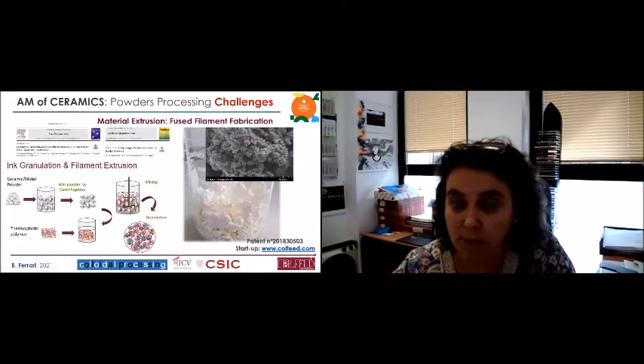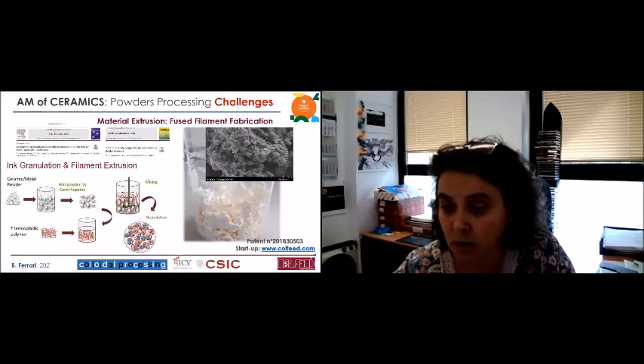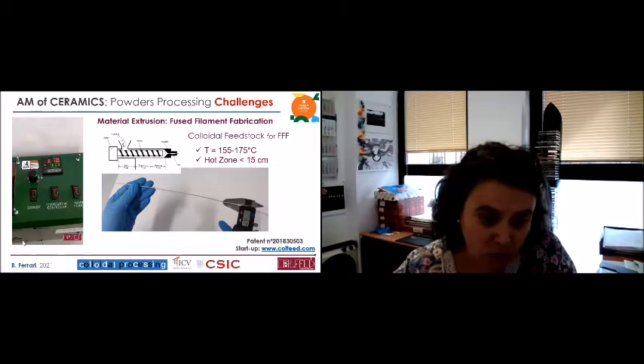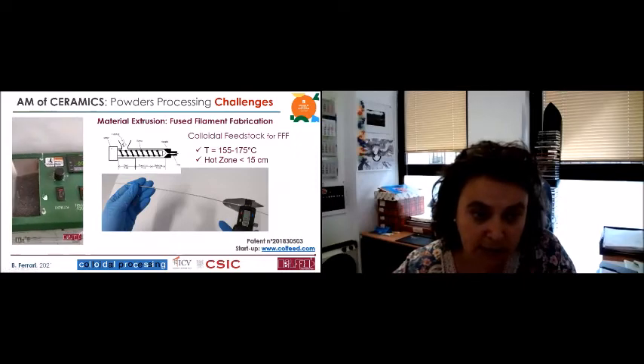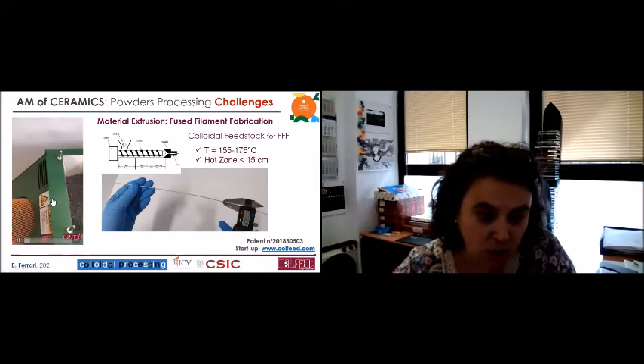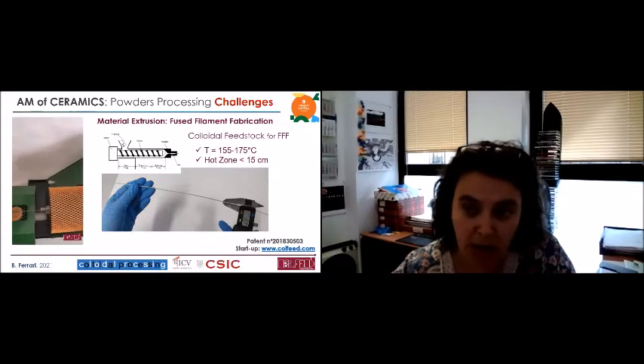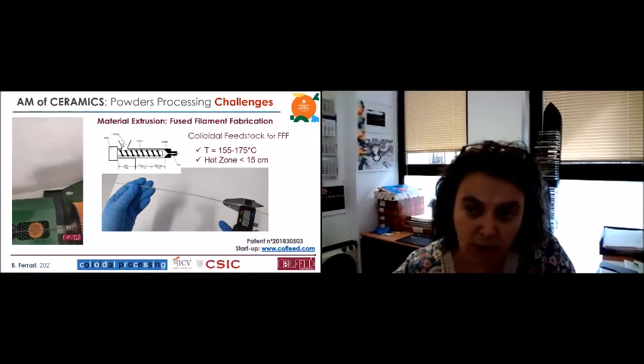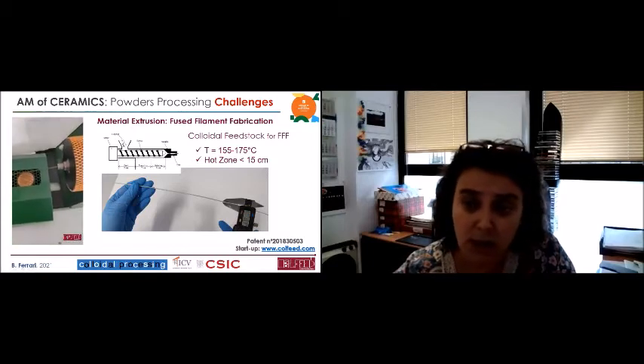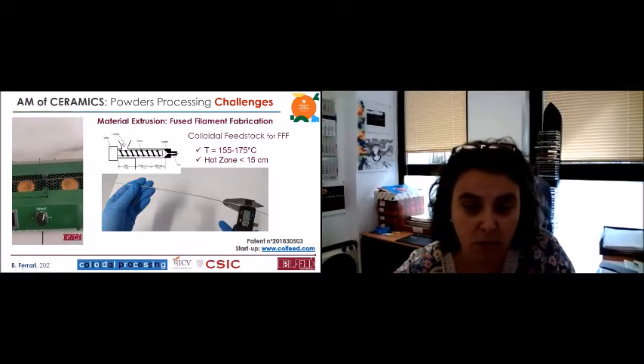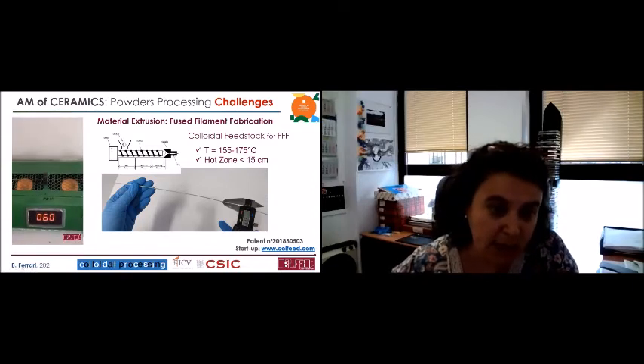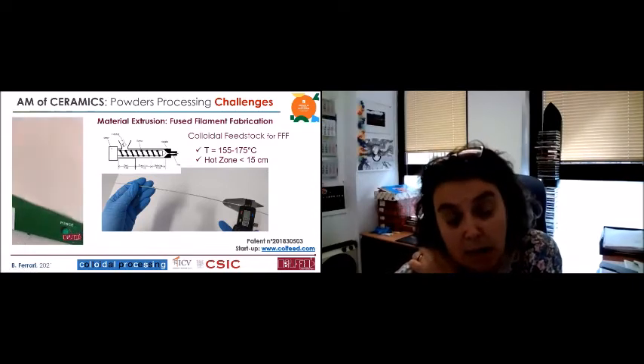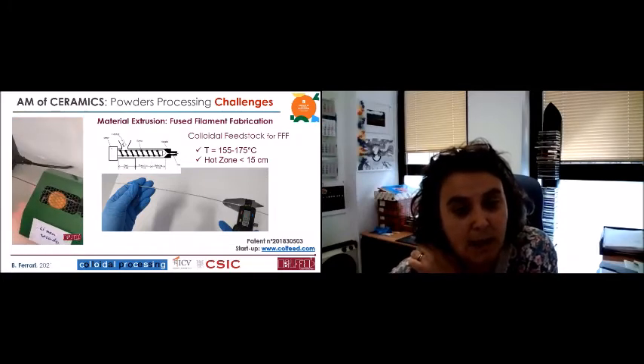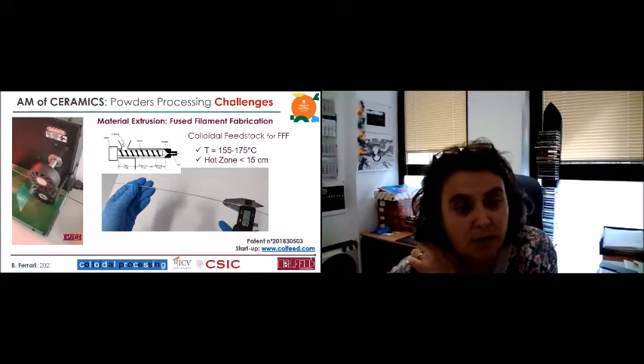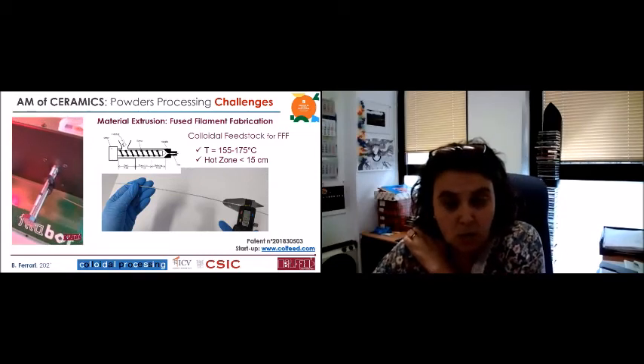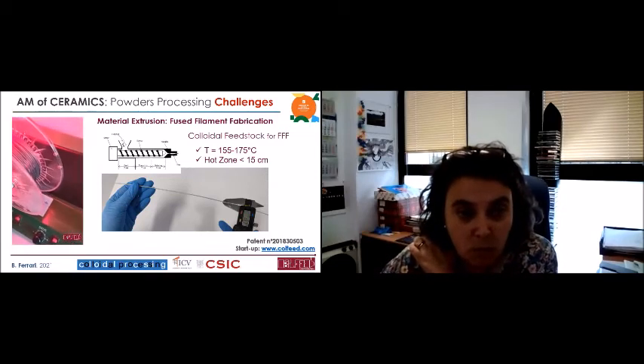And we use this kind of granulation. We prepare the suspension and mix. So in the beginning of the talk, we have these granules, and with these granules we prepare this kind of filament. You see here the granules in a small extruder we use in the lab, right? That does not have a too huge barrel. We have a hot barrel of 15 centimeters, and we work around 155 to 175 degrees C here, and you are going to see that we are able to make this kind of filaments and prepare them for printing, right? So you can introduce in this filament whatever particle you want, right?